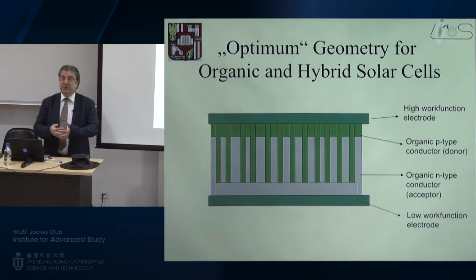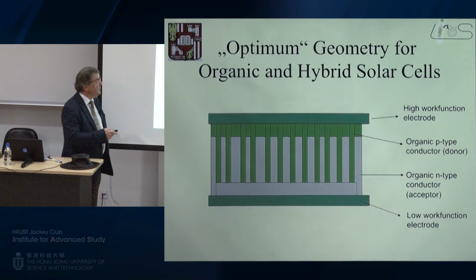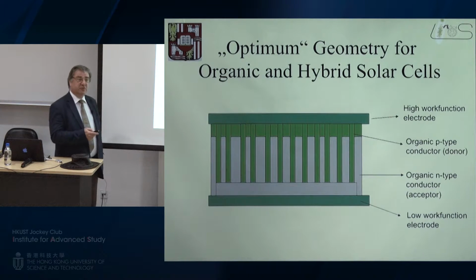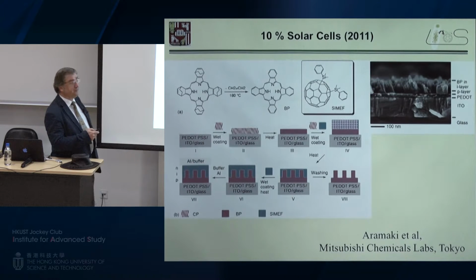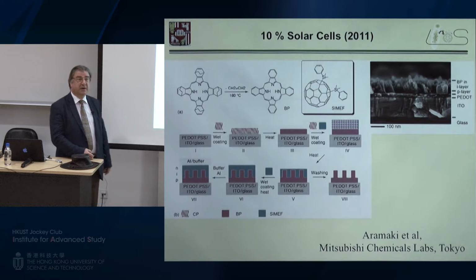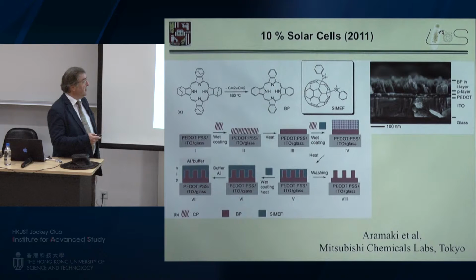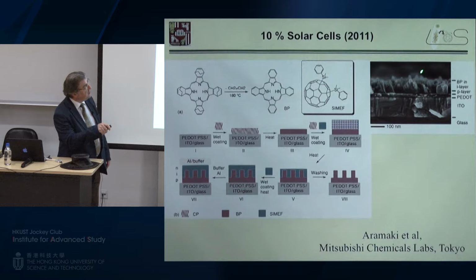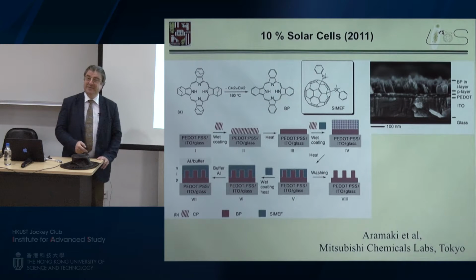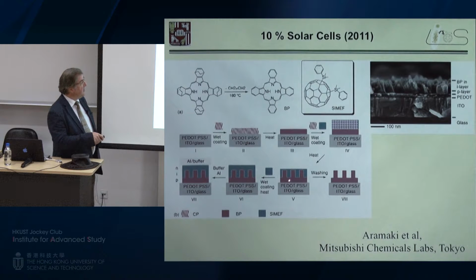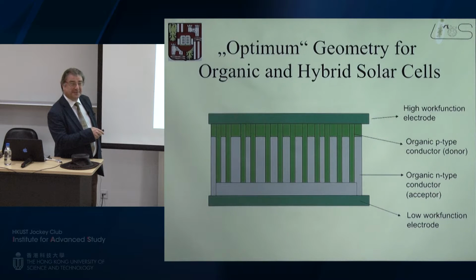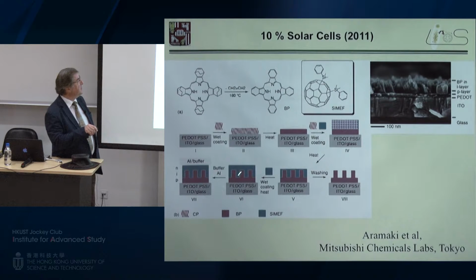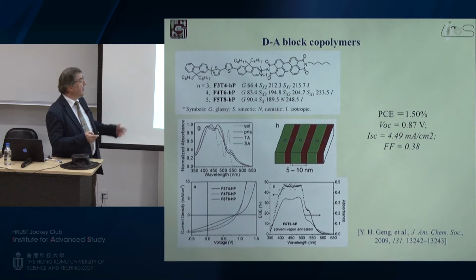So what do we need? We need order in this interpenetrating network. And on this point, it's the picture I was showing, good 20 years ago now, and somebody did it. This somebody is Shunji Aramaki at Mitsubishi Kasei in Japan. This fellow made precursors of benzoporphyrins, and if you heat them up, they basically turn into the real benzoporphyrin, and they create these nano needles coming out of the surface beautifully, and you can fill the rest with the acceptor. That looks very much like the cartoon I was showing. To my opinion and knowledge, this is still industrially very close, getting to the order of a 10% solar cell.